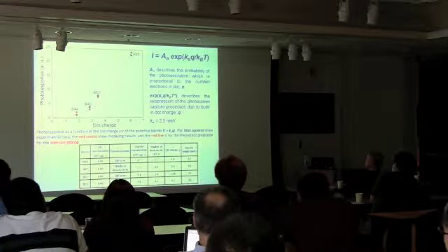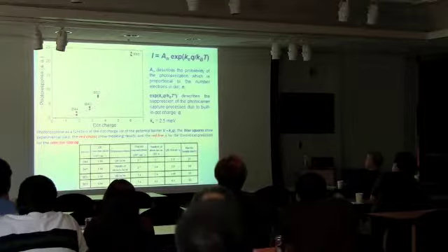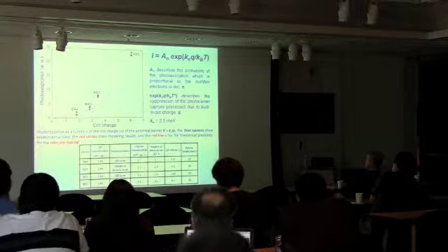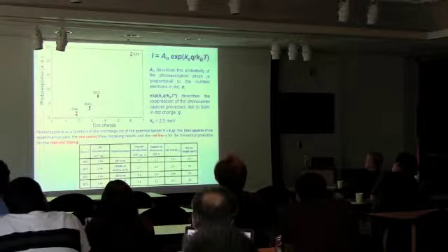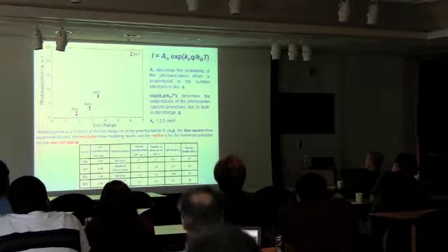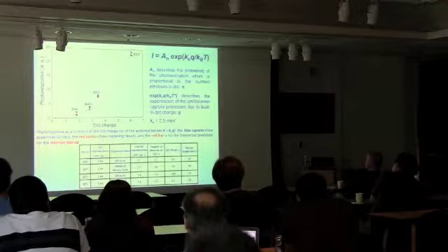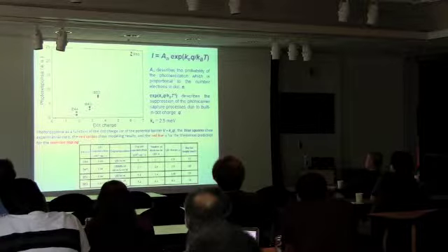With increasing the dot charge, we increase the photoresponse of the detector. And it's due to two reasons. The first reason is very simple: the more electrons, the higher the absorption from the dots, because electrons absorb the light and contribute to the current. The second reason is really the increase of the barrier.